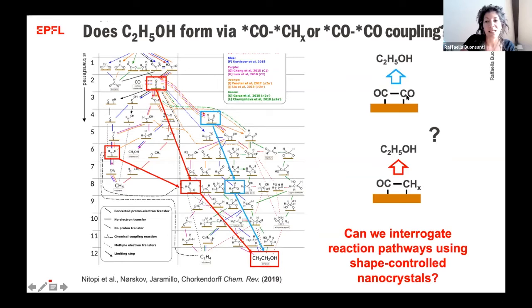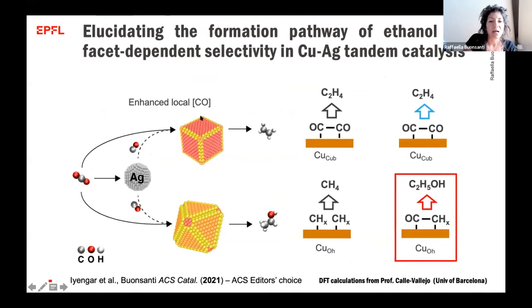In one case, they suggest that alcohols form via CO-CO coupling. Other researchers suggest that instead alcohols form via CO-CH coupling. And the way in which we try to address this question is by combining copper cubes and copper octahedra with silver. This scheme is referred to as tandem catalysis because here the silver produces CO.